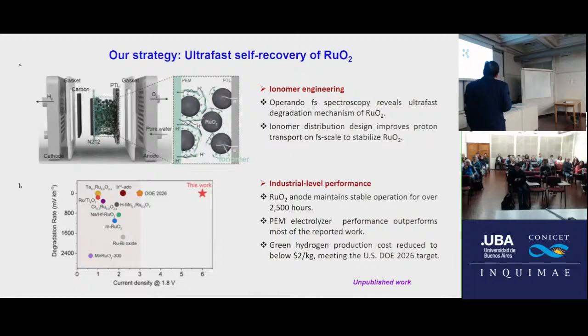Okay, in our system, you can see we use an ionomer coating on the surface. In that case, we can make this catalyst run a long time. You can see modified and not modified: with the ionomer on that, we can run the catalyst 2,500 hours. Very important. You can see the current density is much higher than the DOE requirement. The degradation rate is very low, close to 0. We also calculated the hydrogen cost is $2 for 1 kilogram of hydrogen.